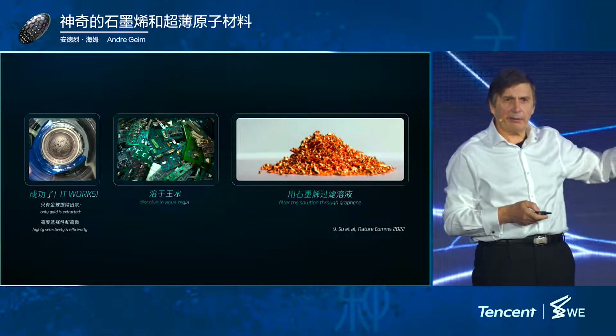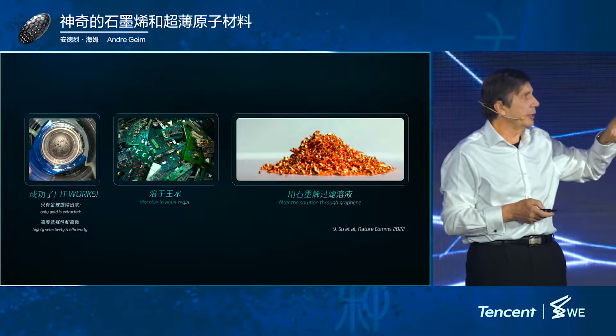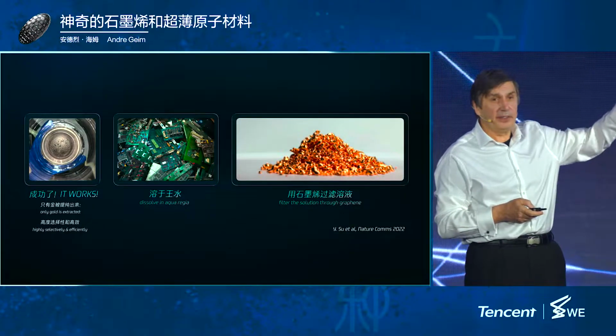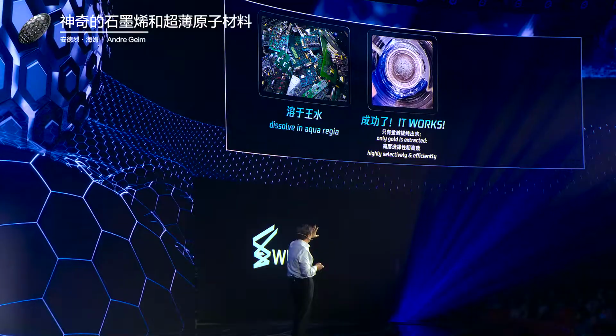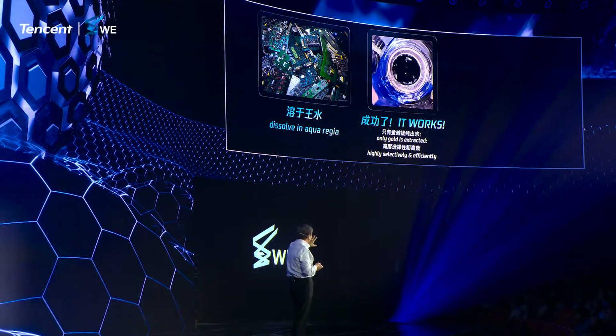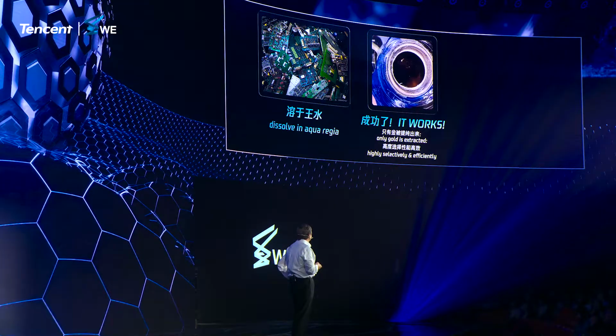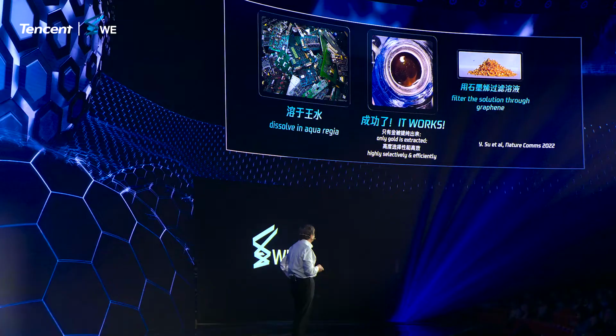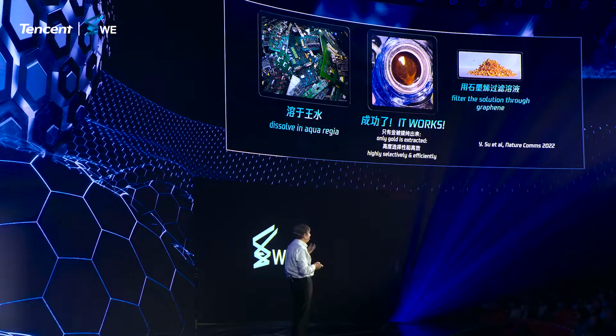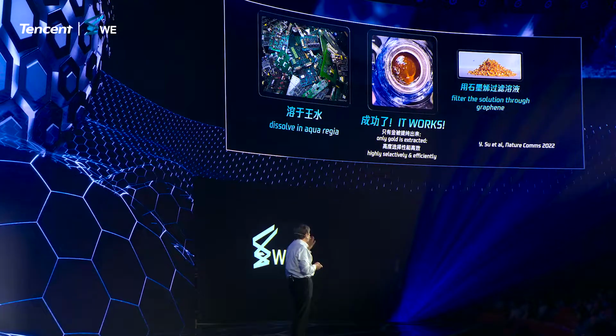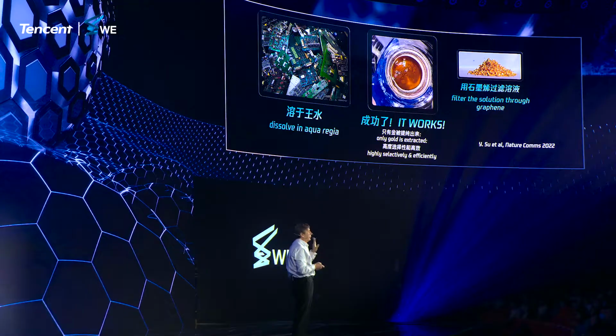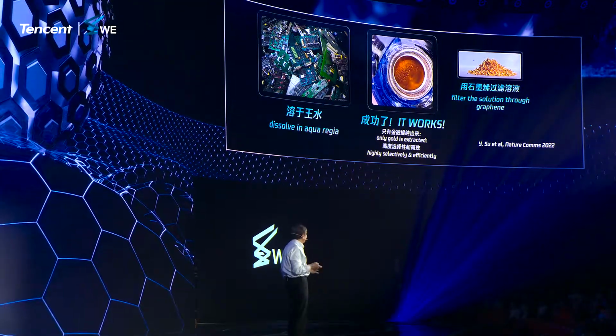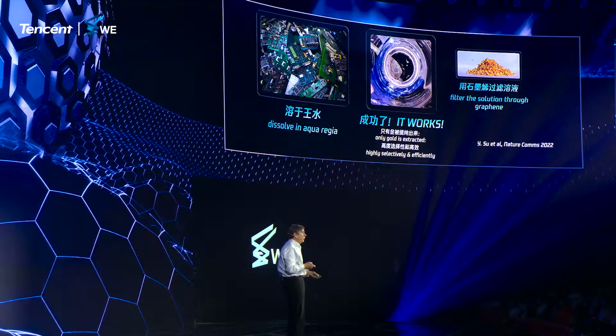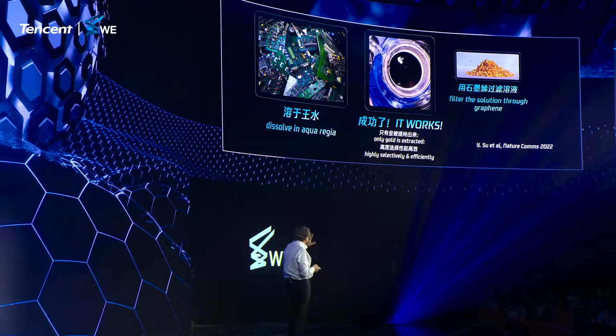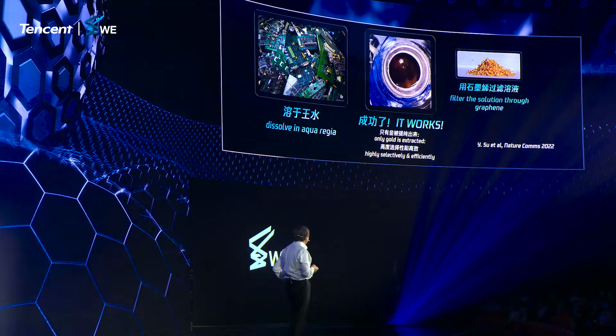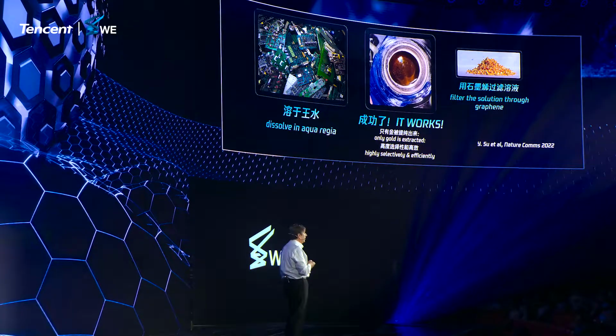If you do the same with graphite, it won't work. With anything else, it won't work. With graphene, you see in the video it gets yellow. This is gold precipitating on graphene and only on graphene. So you take this graphene, literally burn it in air, and you get gold. Very simple, very straightforward, and only gold is extracted. Everything else goes through. So in a sense, it's the Philosopher's Stone at long last. This work was done with my colleagues in Shenzhen, and it's mostly Chinese work, but I like to bring it as an example of what is possible using graphene.